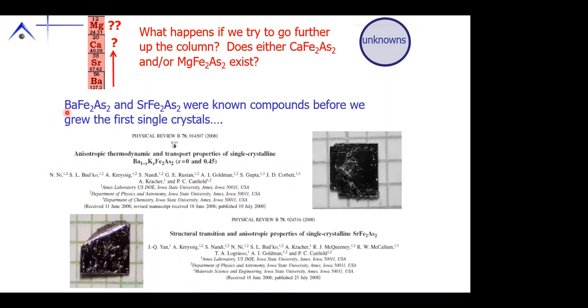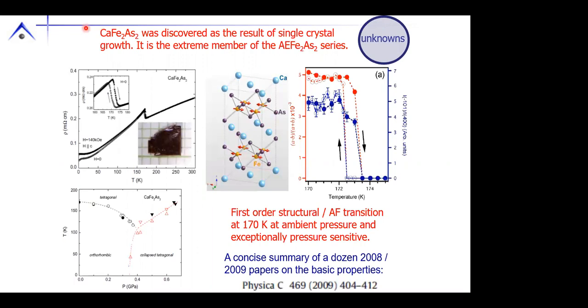Now, what about unknowns? Well, we have BaFe2As2, SrFe2As2. These were both known materials before the iron arsenide superconductors, okay? On the other hand, there was no report of calcium or magnesium. So we tried to grow CaFe2As2 as single crystals out of tin in the same way we grew barium or strontium. And what we were able to do was discover a new phase in single crystalline form. And CaFe2As2 turns out to be the extreme member of this series.